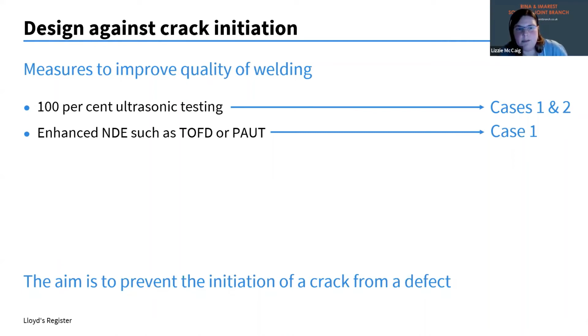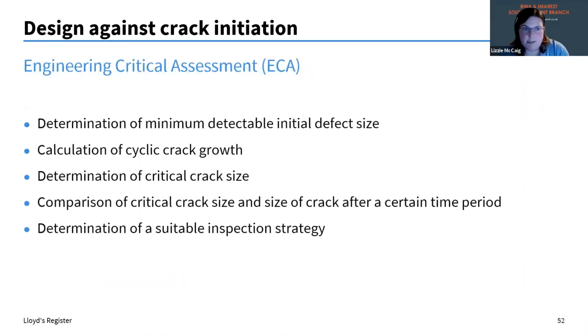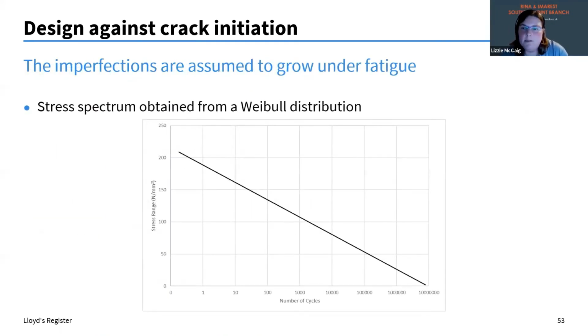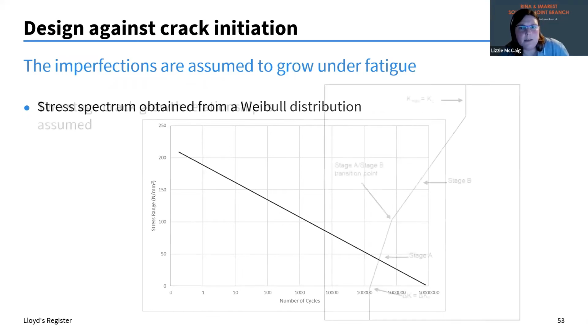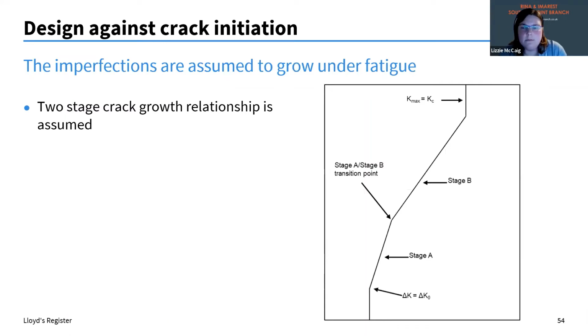And if you're going to use enhanced NDE, you need to know what your critical defect criteria should be. In order to do that, you need to carry out an engineering critical assessment. This is the determination of the minimum detectable initial defect size. Then you calculate the cyclic crack growth, and you determine the critical crack size. Then you compare the critical crack size with the size of your actual crack after a certain time period, and then you determine a suitable inspection strategy. So we assume imperfections will grow under fatigue. We use a stress spectrum obtained from a Weibull distribution because you need to use the loads for the ship, and this is all predictive global loading. Wave loads are stochastic after all. You then grow the imperfections under a fatigue scenario, and we assume a two-stage crack growth relationship, which is all based on a British standard called BS 7910.